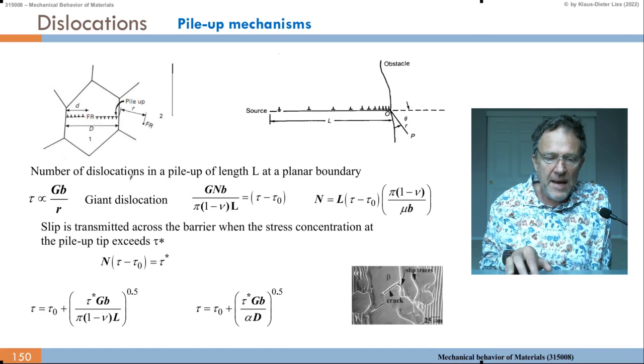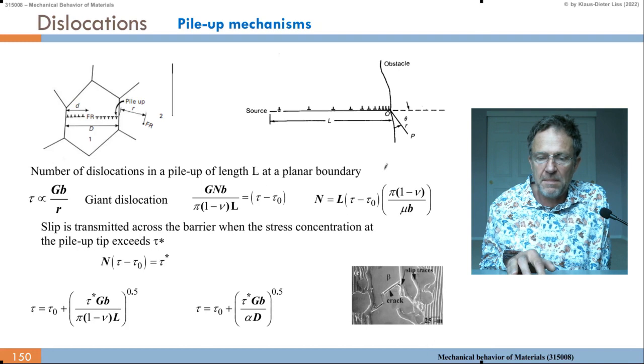So if you have a number n of dislocations in a pile-up of length L at a planar boundary, then we remember that tau is proportional to G times b over r, and we construct this giant dislocation of many, many Burgers vectors. Then we get n times Gb over L. So here it's not a radial function anymore, it's a linear function, so it depends on 1 over L, not on 1 over r, and it's decorated by these geometric terms, pi times (1 minus nu) times L in the denominator.